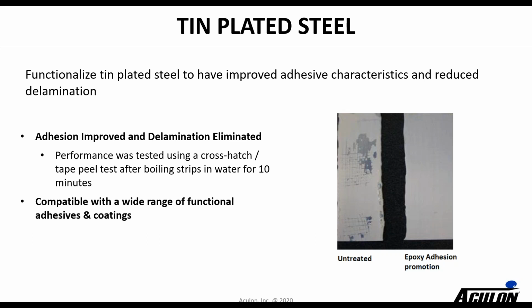is we'll stress the coating. We'll either put it in boiling water or in a chamber and expose it to moisture and heat, and then we'll crosshatch and do a tape peel. So you basically scribe through the coating, you apply tape, you pull the tape off, and then you can see whether or not you have good adhesion. And you can see with the illustration, on the untreated side, you see delamination. You see the coating coming off. On the side where you have the epoxy adhesion promoter, it looks perfectly fine. There's no delamination.